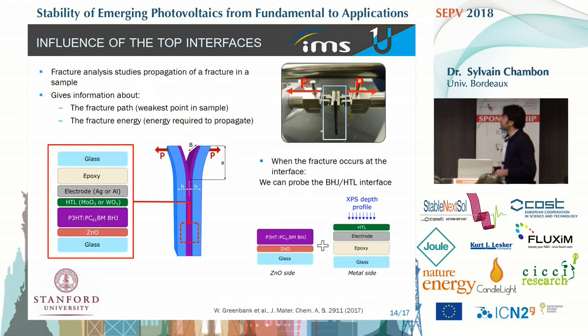And in order to do that, we started a collaboration with Stanford University and Professor Dauskardt's group. We did some fracture analysis of our sample before and after aging. The interesting thing with this technique is that this mechanical testing can give you some information about the fracture path, so you can see what is the weakest point in the sample, but also it gives you the fracture energy.